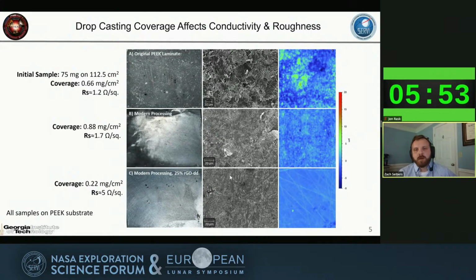On the far left, we have optical images. The middle column here is scanning electron micrographs, and on the far right, we have profilometry. In all three, it's pretty easy to see that there's a big change in roughness with the amount of material that we have here. And then also it's variable. If you look at this middle column here, it's very inconsistent when we start adding a lot of graphene. That's due to issues with the melt processing procedure that I'm not going to cover in great detail here. And then we'll come back to these profilometry images, so just keep that in mind.